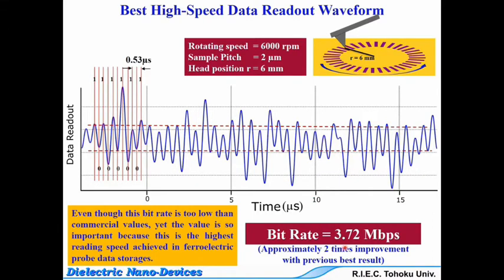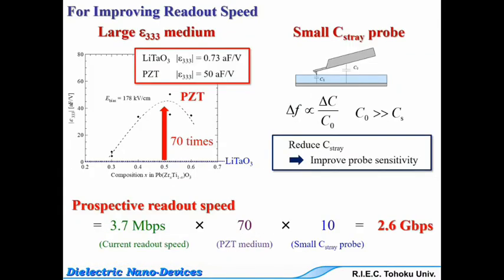3.72 Mbps. And even though this bit rate is too low compared to commercial values, this value is quite high speed in comparison with other ferroelectric probe data storage, for example, using piezo response force microscopy. But anyway, we have to improve the readout speed.